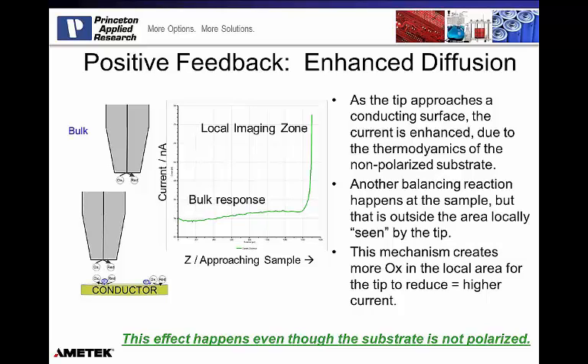This, again, I'm using a specific example of a reversible reaction, and this is A goes to B and B goes back to A in a generic interpretation of the electrochemistry. So we have ox goes to red, red goes back to ox. What does that do then? It increases the local concentration of ox at the probe. That causes another reaction to happen from ox to red. That causes a self-propagating kind of cycling or a positive feedback response. And so the closer I get to the conductor and the probe, the more this recycling happens, and the more current happens. So the higher the localized concentration of ox happens, so the higher current is seen by the probe.